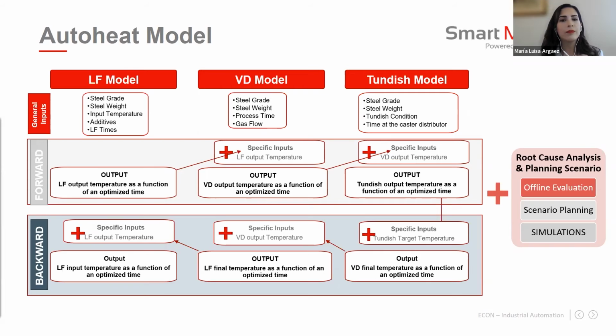These features were processed by analyzing them through an exploratory, diagnostic, and inferential data analysis before the predictive data analysis. Because with this kind of analysis, we can see the feature behavior, detect atypical cases, and select the features that have the most impact on the response variable. The features were normalized to prevent features of higher magnitude from influencing more than those with lower magnitude.